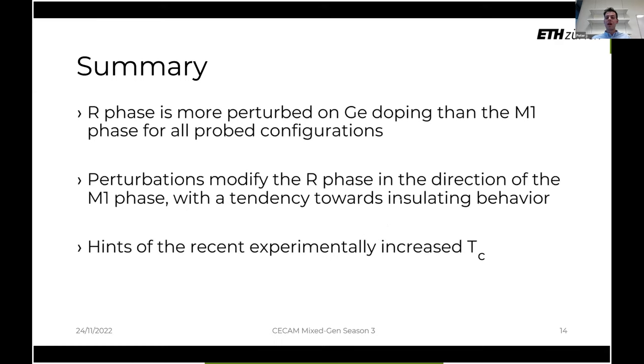And then lastly, this leads us to make a connection to what the experimentalists have found, and that is that it does seem that the monoclinic phase is more stable, or less perturbed, under germanium doping than the rutile phase, which hints at an agreement with this increased transition temperature, since it is the low temperature phase that could outlast the high temperature phase for longer. With that, thank you very much for your attention.